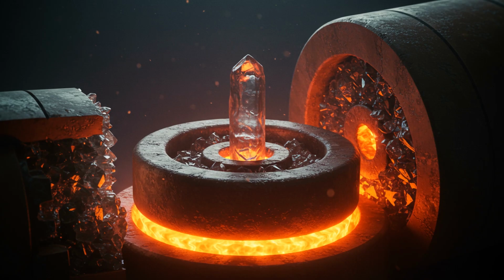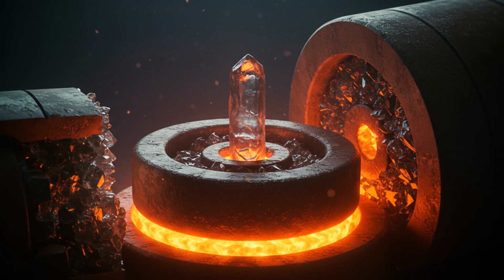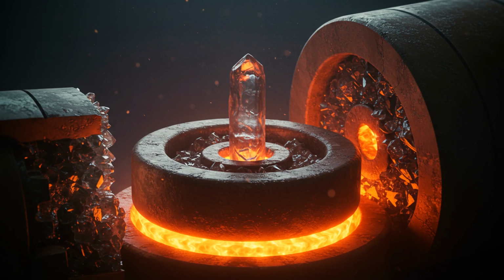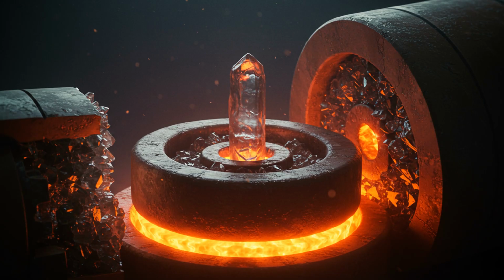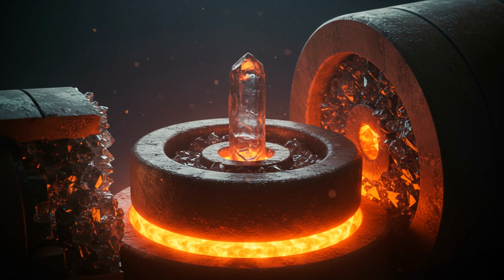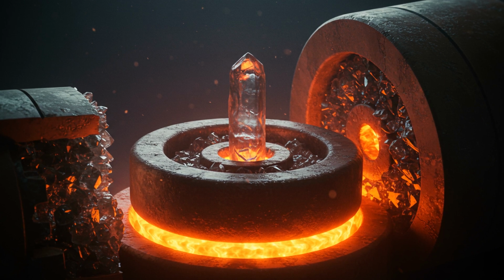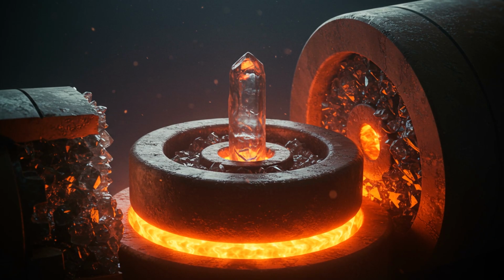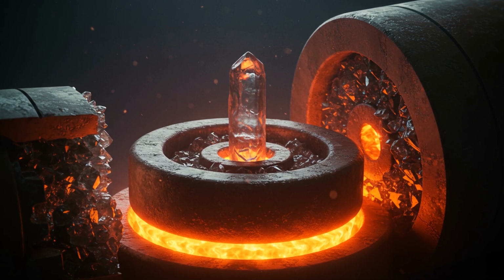At the bottom of the mold is a grain selector, a tiny corkscrew-shaped path. As the metal cools from the bottom up, only one single crystal is able to navigate the spiral and grow into the rest of the mold. This process takes hours of precise temperature control. If the cooling rate varies by even a fraction of a degree, multiple crystals will form and the blade will be scrapped. The result is a part with no internal boundaries, a single perfect lattice of atoms that can withstand the brutal centrifugal force of spinning at 12,000 revolutions per minute, while resisting the softening effects of the inferno. It is a masterclass in molecular engineering.